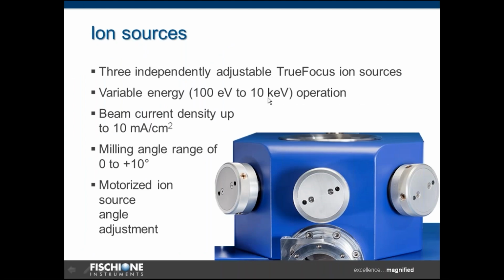The ion sources utilized in the TrionMill are 3 independently adjustable true focus ion sources, the same technology that we're utilizing in our other ion milling systems. The energy range is variable from 100 eV for gentle polishing up to 10 keV for rapid material removal. The beam current density is high, up to 10 milliamps per square centimeter, and the milling angle range is adjustable from 0 to 10 degrees, utilizing motorized ion source angular adjustment, with each of the 3 sources being at the same angle.